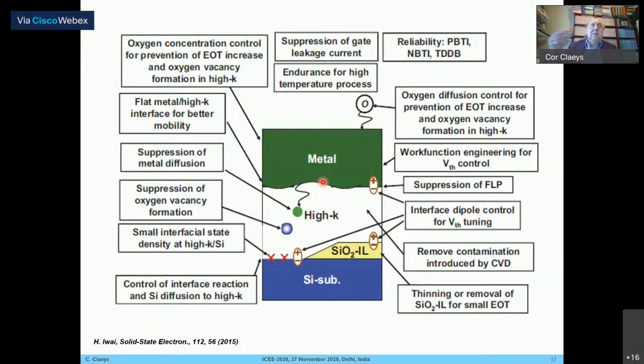You have to look at what is a problem of dipole formation. You have to look at the leakage current. You have to look at the reliability effects. You have to optimize the work function. That means if you work with high K, you have to switch over to the appropriate metallization system. So there are a lot of parameters that must be investigated and optimized before you can introduce a new high K material into a commercial device. And today we can say that the most common high K dielectric is a hafnium-based dielectric. Although at the research and development level, a lot of other high K materials are under investigation.